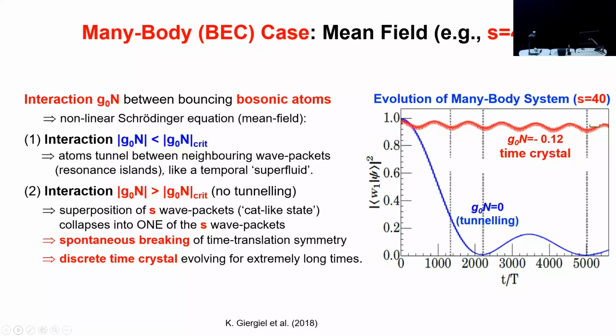So here we show this for S equals 40. This shows the case where you have zero interaction, you get tunneling, the lifetime goes down, and so on. And you get some coming back, again giving you this bump. And if you apply an interaction which is large compared with the critical interaction, it just continues on forever.